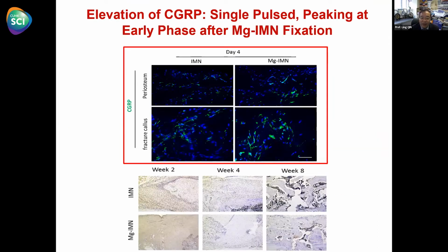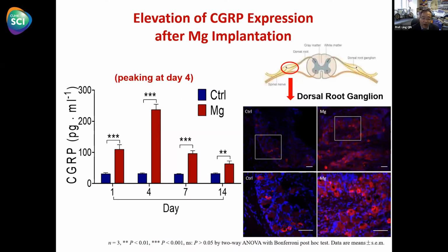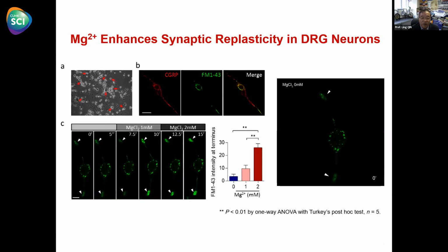So the underlying mechanism is related to the free nerve ending, sensory nerve ending, where we see a lot of CGRP and nerve growth factor proteins highly expressed in the magnesium group. And where are those nerve growth factor and CGRP formed? Basically, it's in the dorsal root ganglion, and we see in the magnesium group the highly upregulated synthesis of CGRP. And then in vitro, we can confirm the release to the nerve ending.